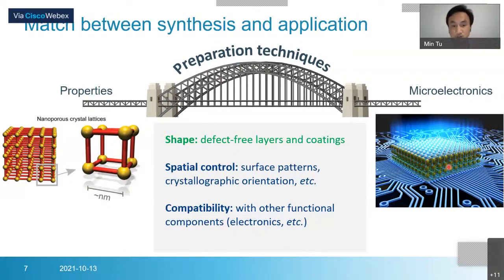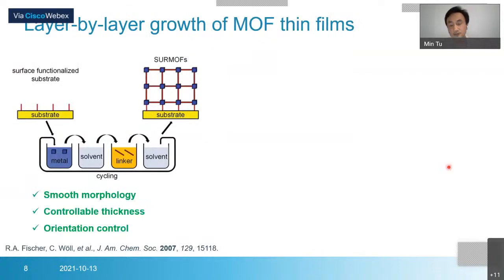First is thin film deposition. So we first aim to develop a technique to deposit defect-free layers or coatings. The first technique we were thinking about is layer-by-layer growth, because we know MOFs are constructed by a metal part and an organic linker part. So we developed a method called layer-by-layer growth. It's kind of a simple method.